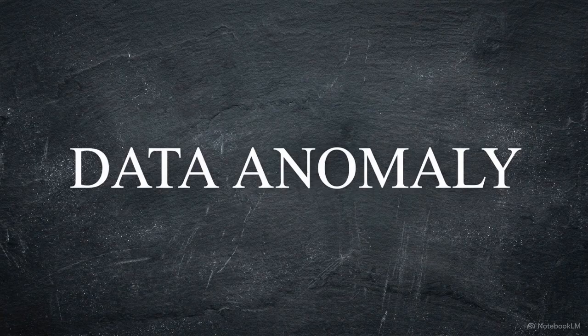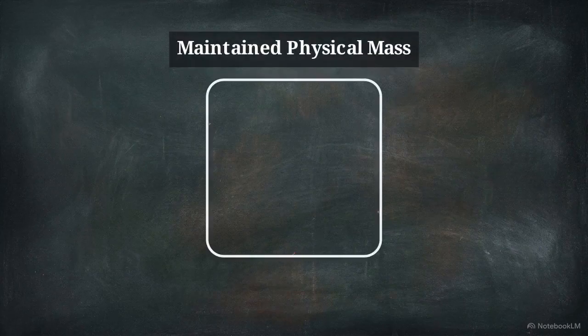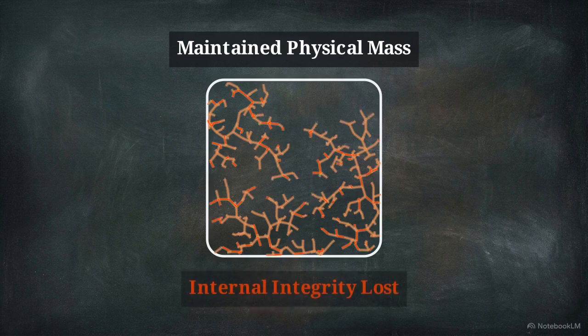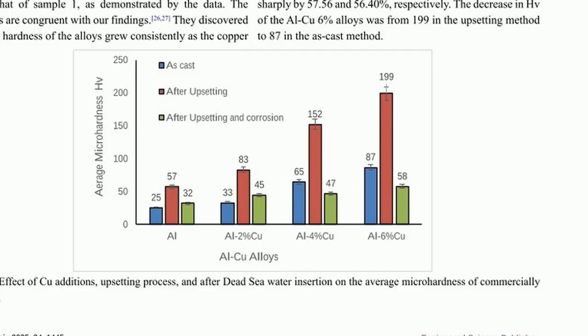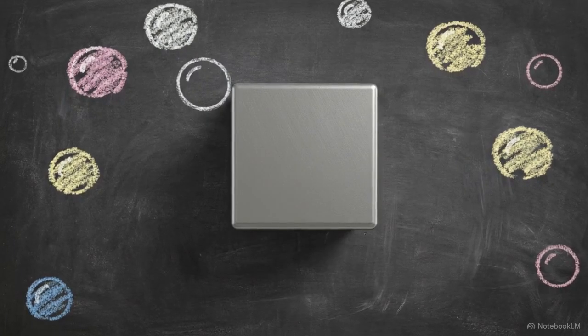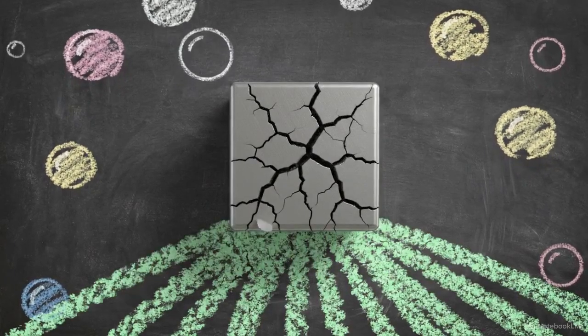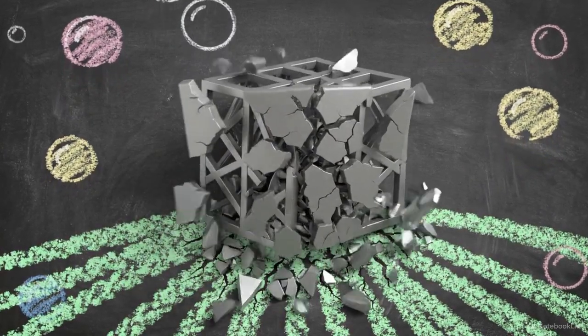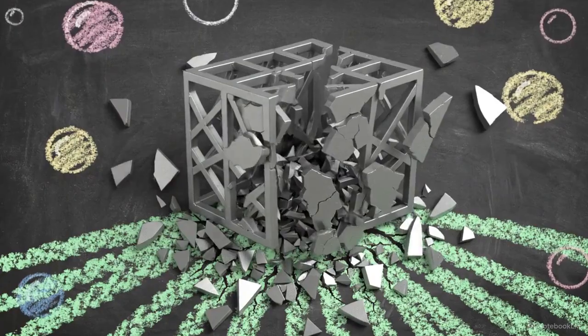But this reveals a critical materials paradox. Maintaining physical mass does not guarantee that internal structural integrity was preserved. This final chart tracks the actual microhardness readings. Look at the plunge from the work-hardened red bars to the post-corrosion green bars, specifically for the 4 and 6% copper samples. Despite retaining its outward physical mass, the hypersaline environment completely degraded the mechanical strength of the most heavily engineered specimen.